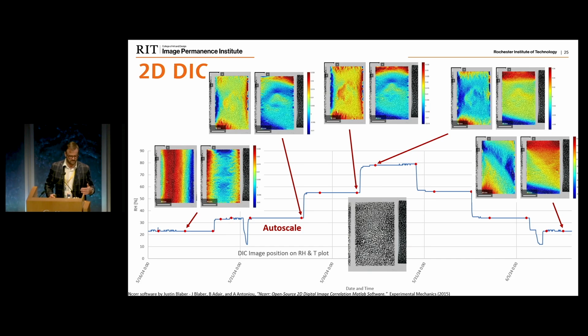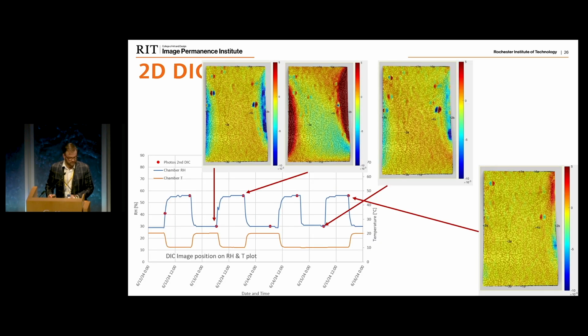So it does correlate with what we've been doing. And finally, with the 12-hour shifts, what you can see here is that paradoxically changing the dew point caused less strain, which was surprising to see. We definitely have to investigate this further. But it definitely shows you that there is potential in this observation.